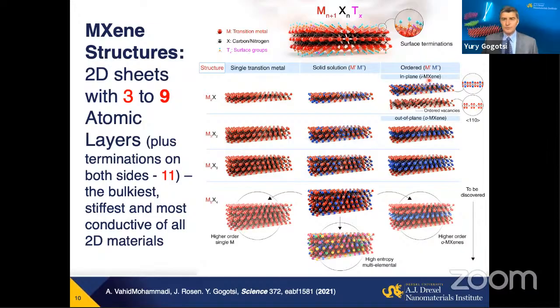And it's not over. We can etch away one of those elements, for example, yttrium or scandium, and leave vacancies, basically monatomic columns of vacancies on the surface, making materials with this type of open surface structure. So you get the idea. Sky is the limit here. Moreover,